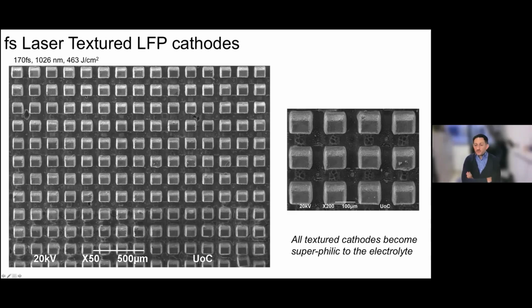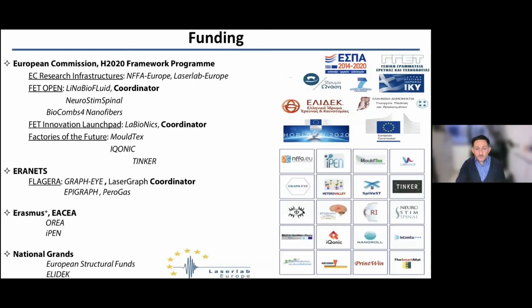So all textured cathodes become superphilic with the electrolyte, and this is encouraging because then we can continue working in this direction and check whether through this texturing process we can increase the capacity of this cathode, of this cell.